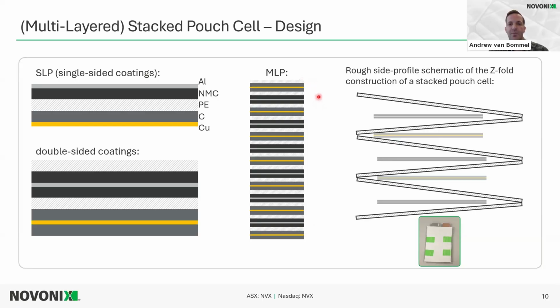stack. So in reality, these separators in the stack pouch cell are not just single sheets. They are Z-folded sheets. So here's a very rough side profile schematic of the Z-fold construction. So you can see the Z right there. There's an anode and a cathode, and the separator will be separating those anodes and cathodes. Clearly, this is expanded, so a real pouch cell would look like this with the 7 layers of anode and 6 layers of cathode.